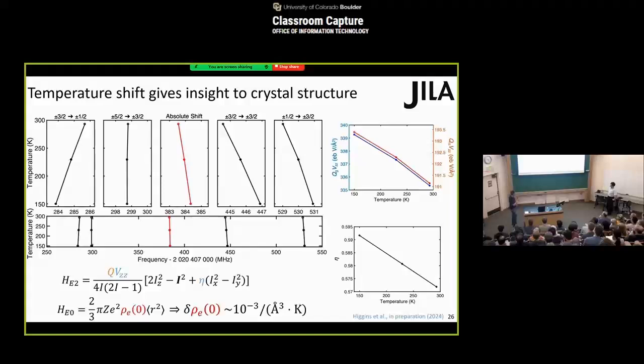But now one interesting thing is that you might have seen this line appears to be a little special, where the temperature dependent shift is less compared to the other lines. We think this is accidental cancellation between the monopole and the quadrupole interaction terms. So this less sensitive line might be a good candidate for a clock transition line, where it's less sensitive to temperature shifts. Opportunity to engineer a crystal structure to cancel exactly this line for multiple clocks.